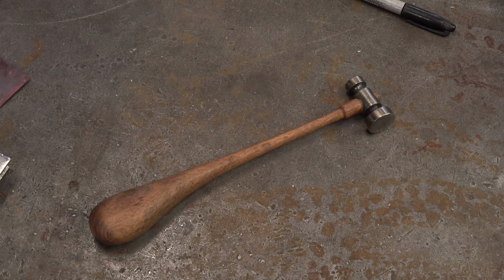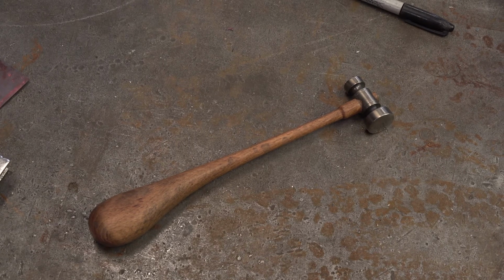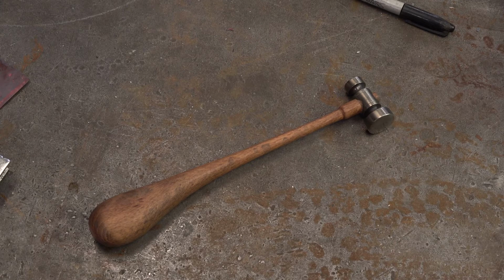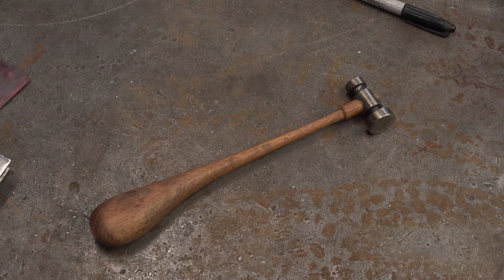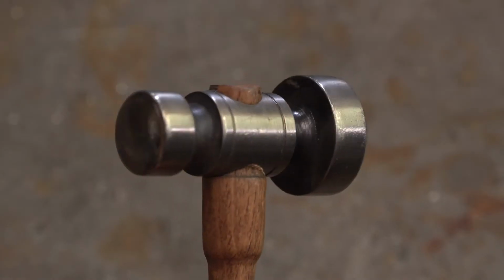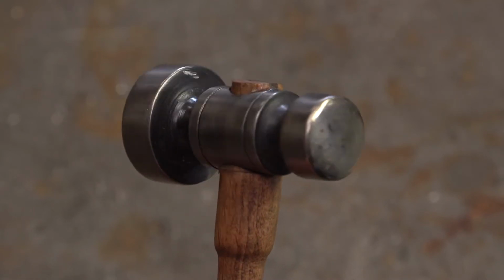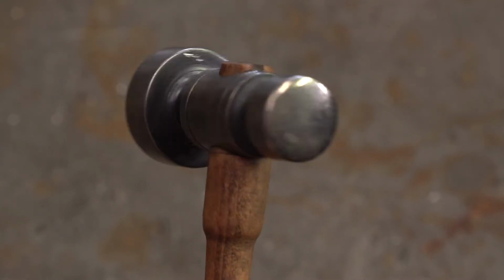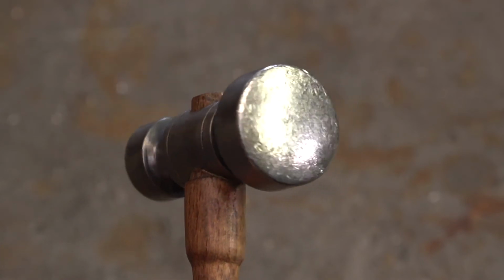This is my favorite little chasing hammer. I made it out of 4140, turned it on the lathe, so it's basically a machining project. But when I heat treated it, I put it in a stainless bag so that it wouldn't get all pitted. And I just took and quenched the whole bag, which is a mistake. You're supposed to rip the bag and pull the metal out of the bag while it's still in the oven and then quench it. And I didn't realize that, so it didn't get as hard as I wanted, but it still works really good.